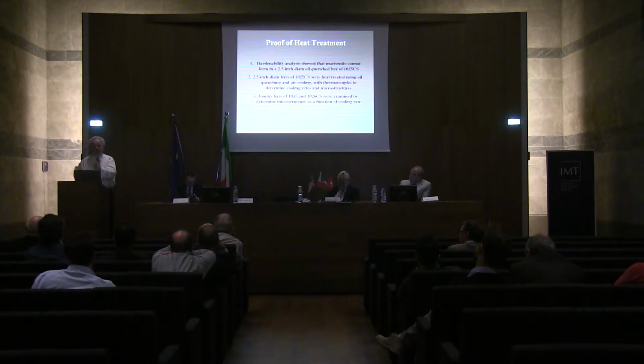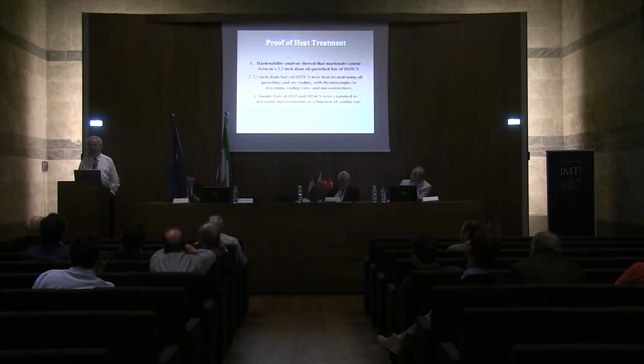Now that doesn't tell you how many cycles there are before the crack started, but nevertheless it would be more conservative, because I can't estimate how many cycles it took before the crack started, than what Harold would come up with. And so when I gave him my results, they fit in perfectly with his model, which is the way things should work when you do good work, but it doesn't always work that way.